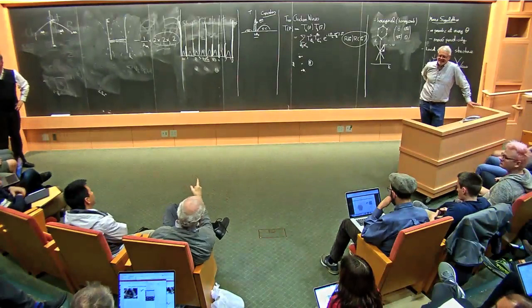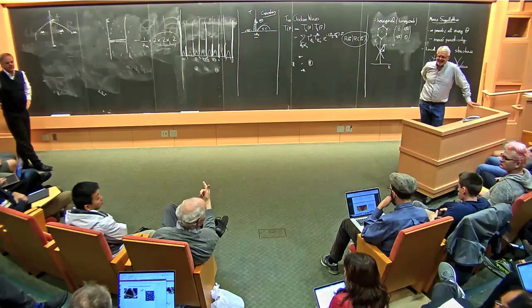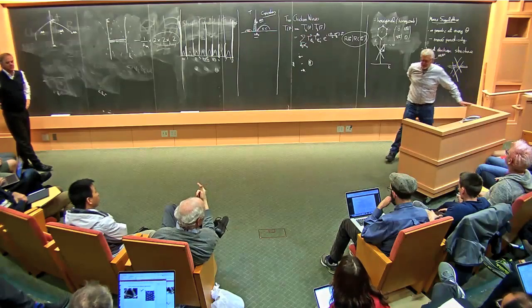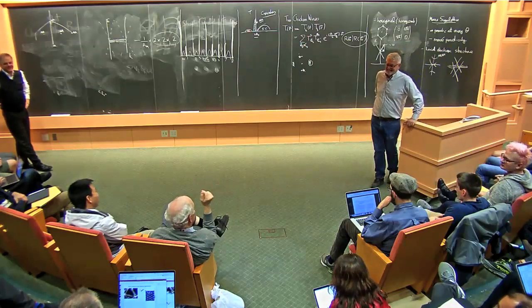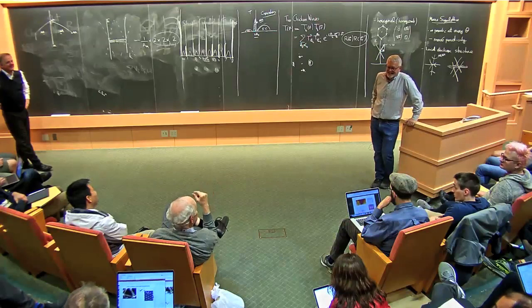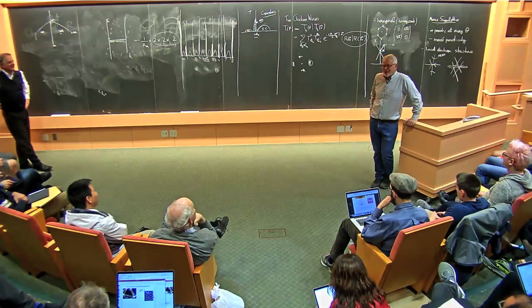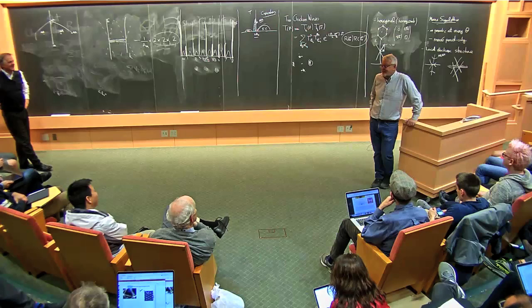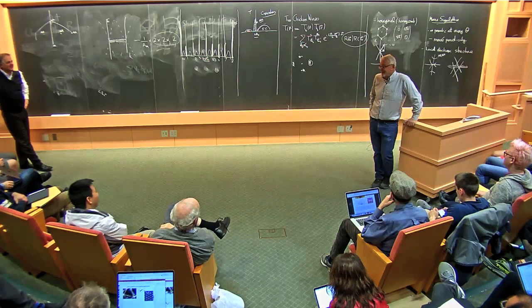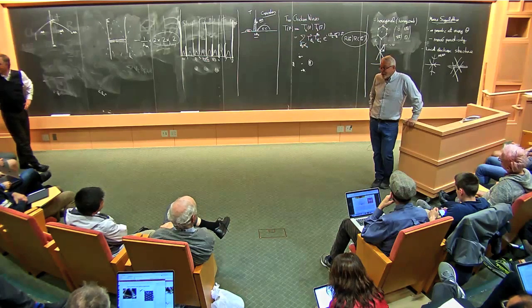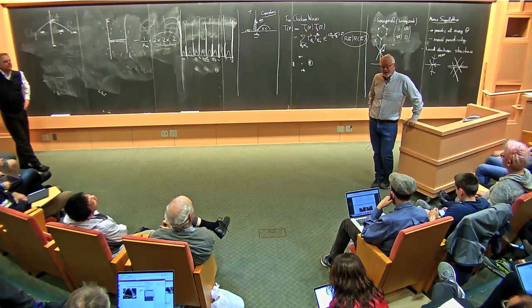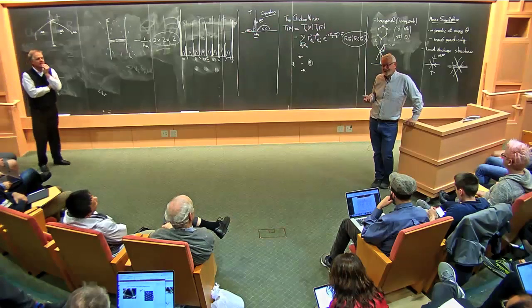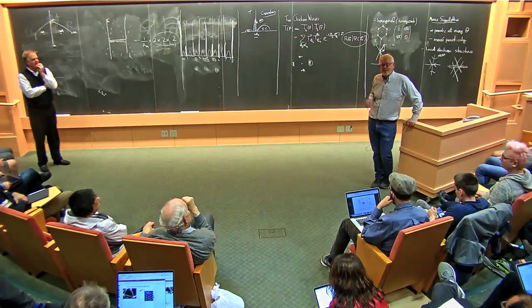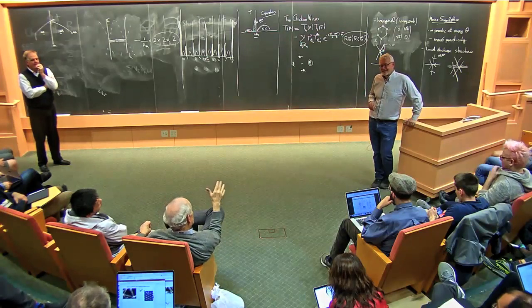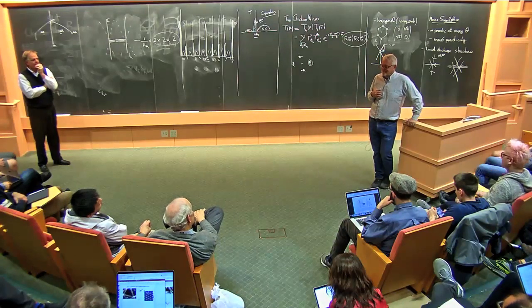By the way, you said it's much higher temperature than the cuprates. Not really temperature, of course, but relative to the Fermi energy. What is it? I think there are some claims, inklings of superconductivity at 5 degrees Kelvin, which is about half a millielectron volt, compared to a bandwidth that varies a lot. I don't think we really know what the bandwidth is, but maybe it can be as small as around 10 millielectron volts. But if you scale it up to the cuprates, for example, what would that mean?